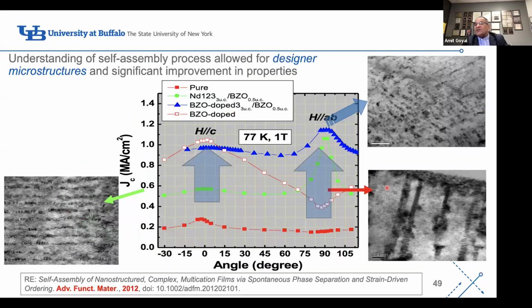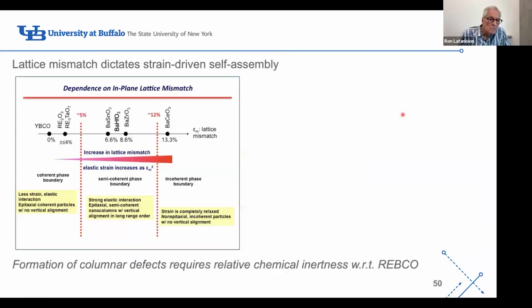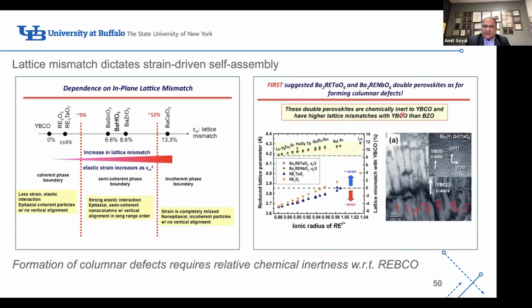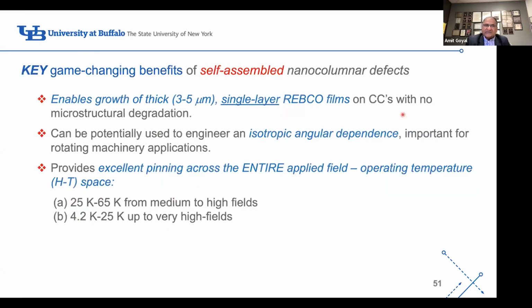Okay, once we understood how this was happening, we can either align the nanorods the way I showed you, or we can modify the strain to align them perpendicular, or we can actually align them in both directions. Again, all of these nanostructural modifications are to increase the performance of the superconducting wire. I won't go through some of this because it goes into a little bit more detail. I'm going to skip some of these slides.